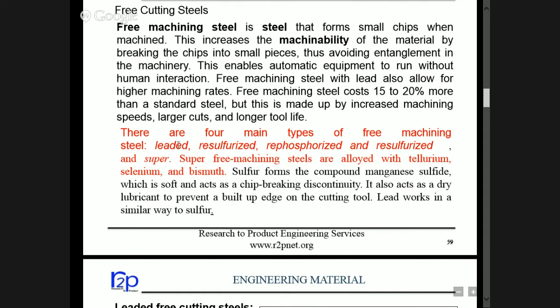Right. So what sulfur does in these is, sulfur forms the compound manganese sulfide, which is soft and acts as a chip breaking discontinuity. It also acts as a dry lubricant to prevent a built-up edge on the cutting tool. Lead works in a similar way to sulfur. The intent is to avoid the long curling chips of the cutting material. We want only small pieces that break down, so that we can give more feed and depth of cut. Otherwise, those chips will entangle with the tool or the workpiece, and we cannot run the machine at a high productivity rate.